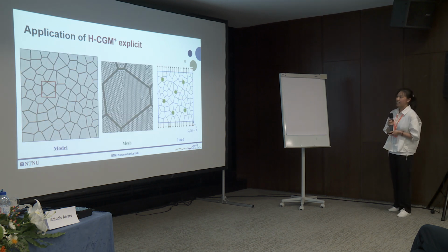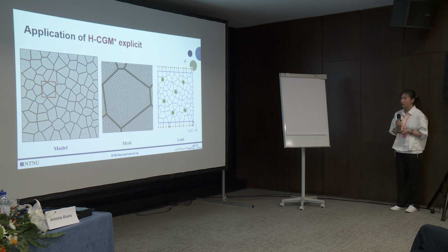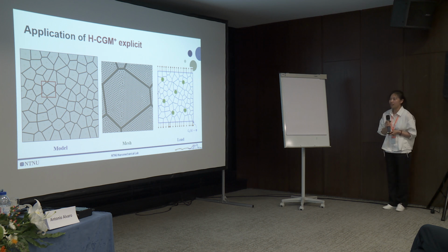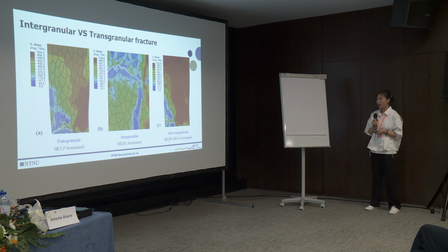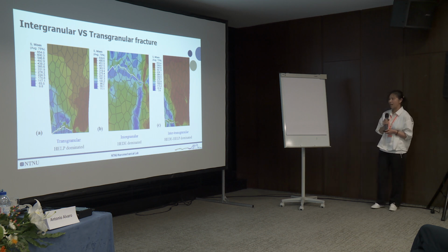And then I will show the application of the explicit algorithm. Here we simulated a polycrystal, and it's also a pre-charged case. We captured intergranular fracture, transgranular fracture, and a mix of these two fractures. The result depends on the hydrogen concentration, the trapping effect, and the specific microstructure.